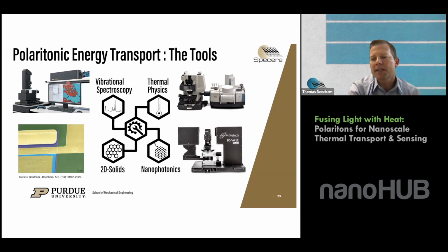And so this allows us to take Raman, photoluminescence, and photocurrent mapping measurements down to a diffraction limited spot size, but we've been able to image at Sandia down to about 200 nanometers. We can also do that transient, and we can do that cryogenically all the way up to 600K. We'll also be adding on to our ellipsometric capabilities here by bringing in an infrared variable angle spectroscopic ellipsometer,